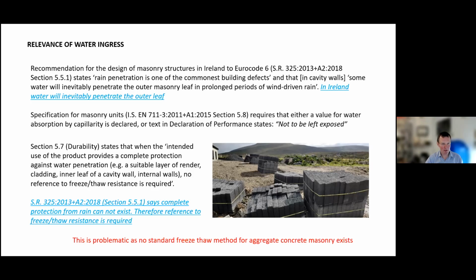Section 5.7 of this EN 771 part 3 on durability says that where the intended use of the product provides complete protection against water penetration, i.e. a suitable layer of render, cladding, inner leaf, or cavity wall or internal walls, no freeze thaw resistance is required. But where it is exposed, there should be a freeze thaw test. Now, this is, to me, a bit of a conflict because the Eurocode is saying inevitably the outer leaf will be getting wet. The data says they are getting wet, but the 771 suggests that it might be possible to protect them with render. And in that case, you don't need to require freeze thaw resistance. Here is one of the big problems we face, and this is that there's no standard freeze thaw method for aggregate concrete, masonry concrete. There are for other materials, but not for these blocks.